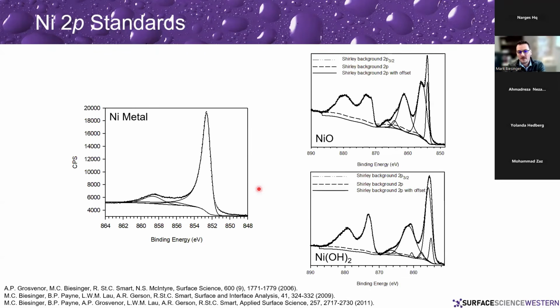Next up is nickel, and you can see that there's a lot of shape to these peaks. These have both multiplet structures here, and then shake-up structures here. So we've got information coming from these two different phenomena. If we look at our metal, we have an asymmetric peak shape, but we also have some satellite structure that we have to model and put into the model for area under the curve.